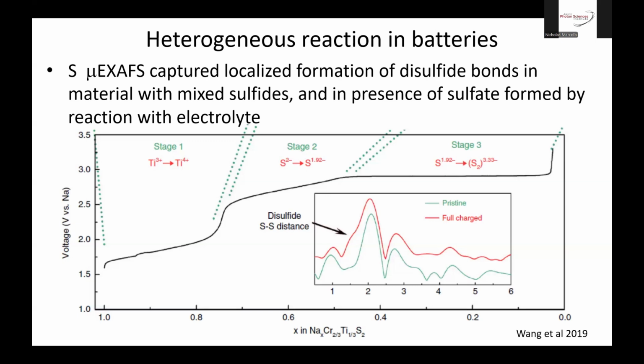And also the samples were mostly very thick and self-absorbed, so we had to find the best behaved particles with the right amount of sulfur in them. And so this is the XAFS, and in the fully charged state, you see there's a little shoulder in the XAFS here that indicates the formation of the disulfide bond, where the main peak is from the metal sulfides, and the peak to the left is from the oxidized sulfur from the electrolyte. So teasing all that apart, that was a pretty challenging experiment, but it could be done.